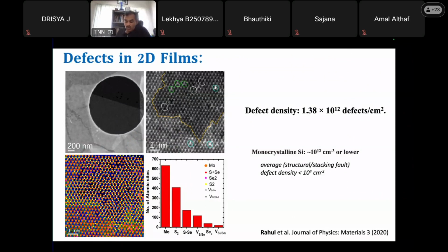But now, when you talk about new materials, I told you the defect is inevitable. It's very difficult. And this is not only the issue with monolayer 2D materials like TMDs or graphene or whatever system. It is the issue with all new materials. Even in perovskites, defects are one of the major problems. Defect density is of the order of 10^12 defects per centimeter square. But for monocrystalline silicon, it is 10^12 per centimeter cube or lower. So defects are quite high, and different types of defects are one of the problems.